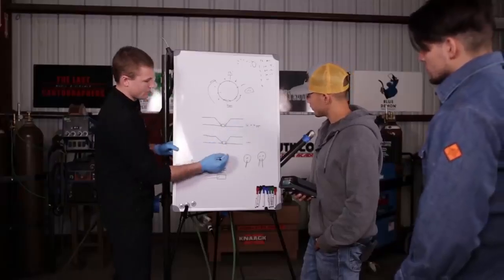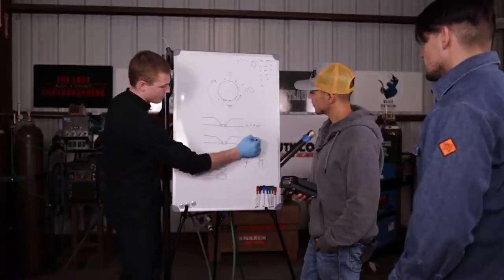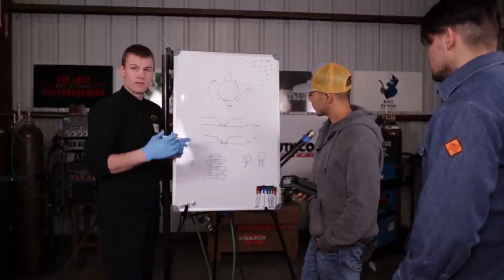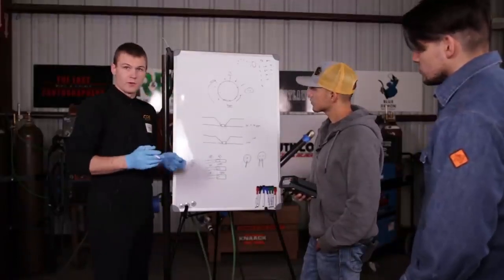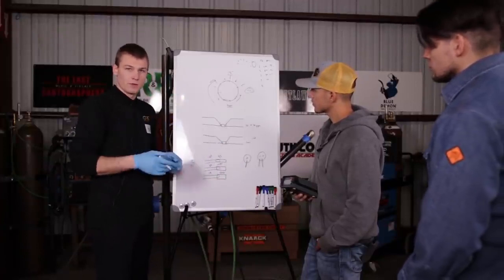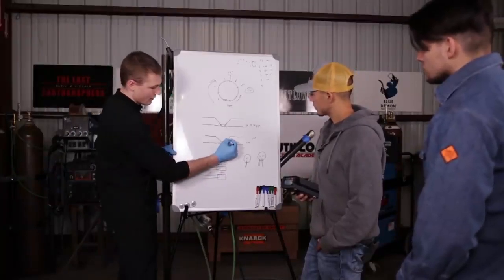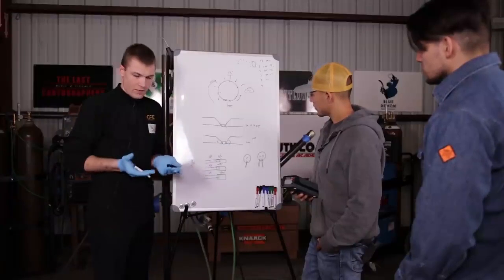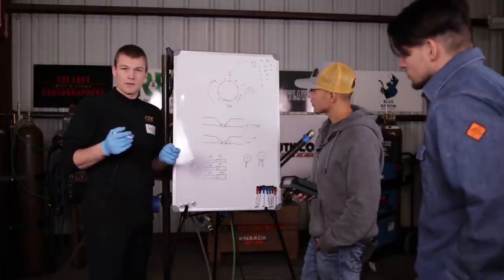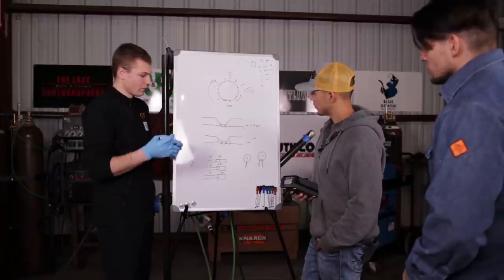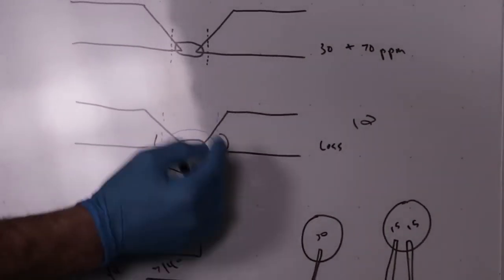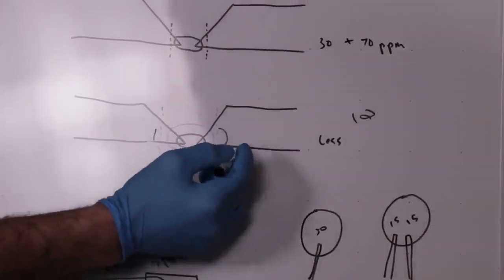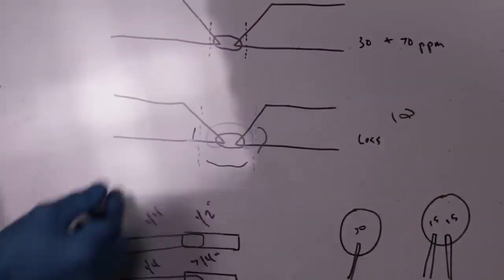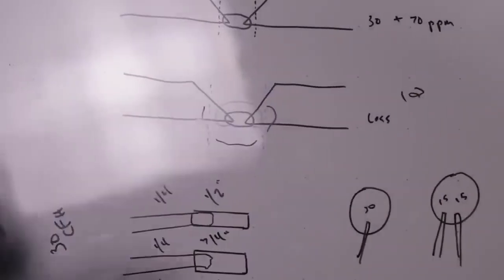When you do the hot pass, the parts per million of oxygen are going to be much better, maybe about 10 parts per million, 11 parts per million. The purge quality is going to be a lot better. And also the hot pass has a wider heat affected zone, and you're going to be heating up the root pass, including the heat affected zone of the root pass. Because the heat affected zone is wider than the root pass, and because the parts per million of oxygen for the hot pass are going to be better than when you were doing the root pass, you have a good chance of having a higher quality atmosphere while doing the hot pass. So it may remove some of the heat tint that the root pass had deposited when it was at a worse parts per million of oxygen.